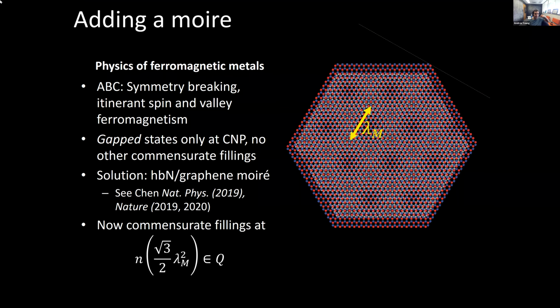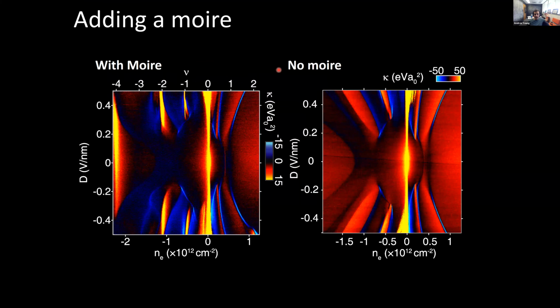Yes, so you can add a moire, indeed. The basic takeaway is that when you add a moire, the isospin physics doesn't change much. What does happen is that we have these quarter and half metals that can occur without a moire. If your moire period happens to line up such that, for example, you're at nu equals 1 of the moire at a density where even without the moire you have a quarter metal, then you'll get a gap, because you only had a quarter metal, so you just need 1 electron per site to be in a gap state.